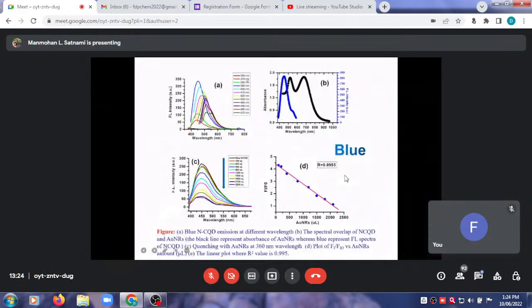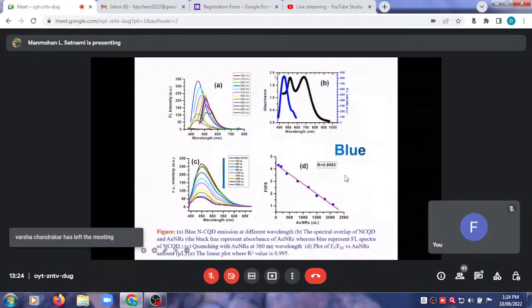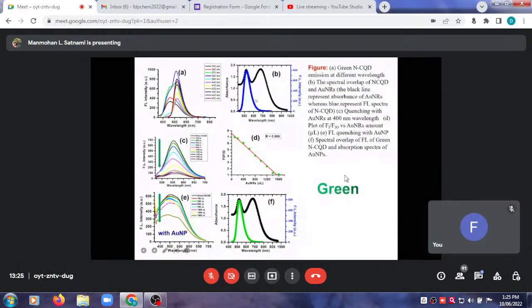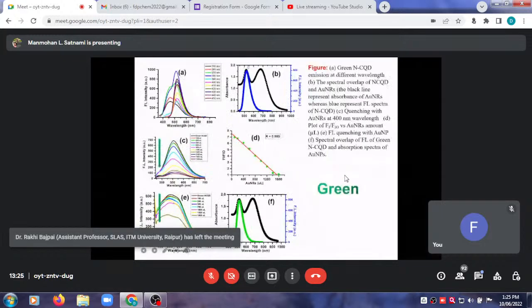What we design? We prepare carbon quantum dots, 4 carbon quantum dots: blue emissive, green emissive, orange emissive, and red emissive. Okay, and we try to see that if carbon quantum dot is blue emissive, then there could be a little bit overlap with the absorption spectra of gold nanorod at 520 nanometer. And this is remain. I skip this. Okay, you consider only this figure. Okay, then green. See, the green carbon quantum dot emits at 520 nanometer. So this fluorescence spectra of carbon quantum dot is exactly overlapping, close to 100% overlapping with the first absorption band of gold nanorod.